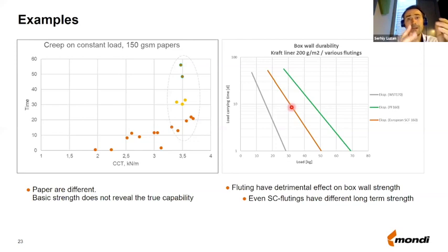And therefore, you can see that actually a small change, you can think you just change the core of the corrugated board, but this change may actually have quite a big impact on the lifetime of your box. The natural question you may have is whether liners will also have such a big impact on the lifetime of the corrugated board and boxes. The answer to this question is yes. Liners also have a big impact, but based on our experience, the fluting has even bigger impact on the lifetime of a box compared to the liners.